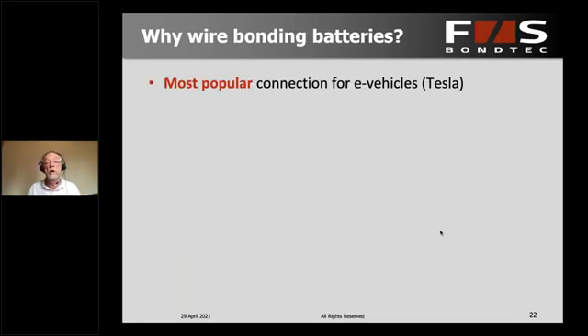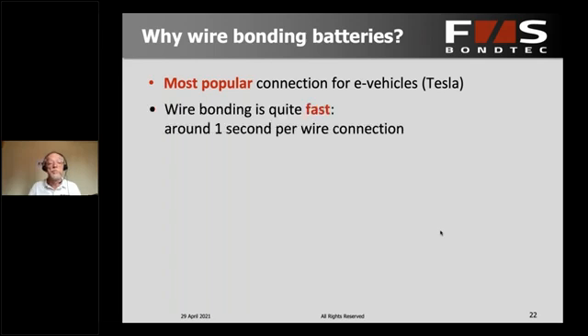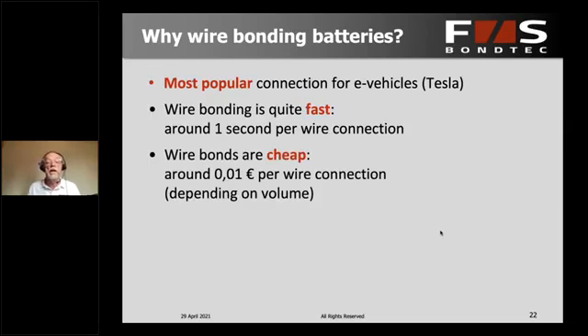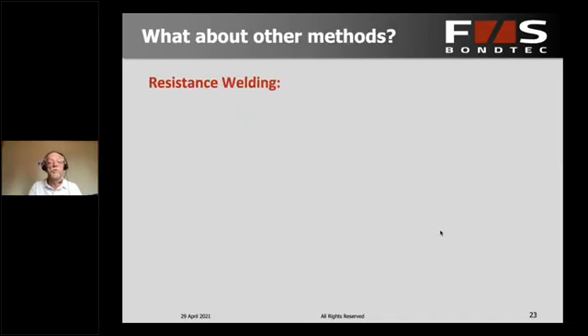that's the reason why, really, for e-vehicles, at least for those with the cylindrical cells, just like Tesla's, wire bonding is by far the most popular connection technology. It's also quite fast, as you saw from the videos. The typical connection speed is something like 1 second per wire, and it's relatively cheap. Depending on the volume you use, you could count on having something like a cent or so per wire connection, depending on the length of the wires and so on. But that's a good rule of thumb to use.